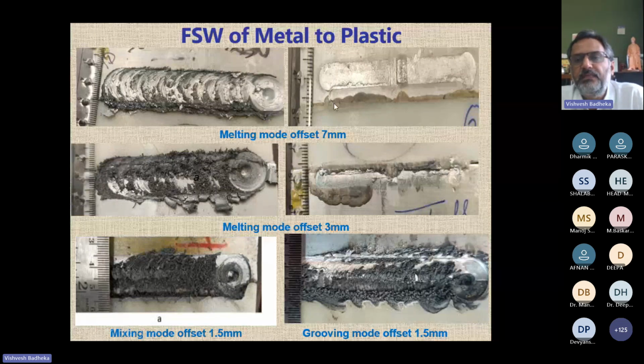To make you understand, you see here, this is the joint line, and my tool is doing a processing kind of thing here because I'm far away from the joint line. You know there is a large difference in the melting point and the mechanical property of metal and plastic. In this case, it is aluminum. So aluminum melting point is 660. I'm doing stirring and mixing here, which leads to the melting of plastics and joining of plastic. You can see my contact with the plastic is very far. Only maybe because the shoulder is bigger, there is some contact with the top material, and material is getting dragged because of the shoulder, and it is getting mixed in the top region. So this is called melting mode because there is no contact.